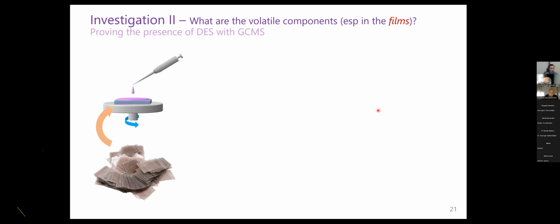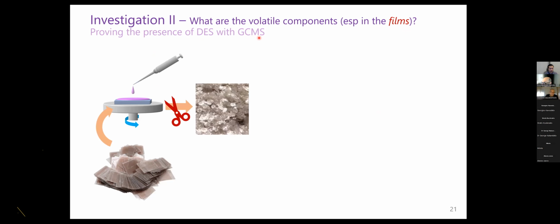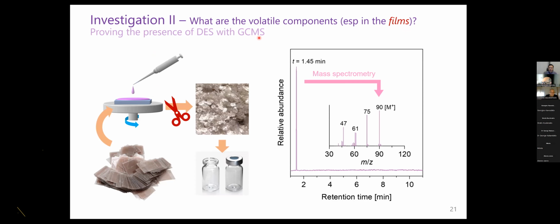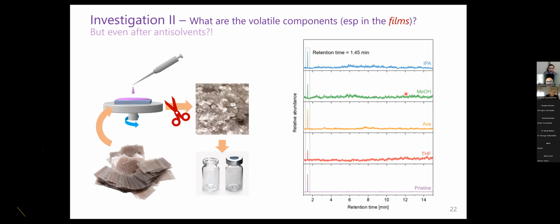Then we also studied the film state. In this case we tried to prove the presence of diethyl sulfide in the film state using gas chromatography mass spectrometry. We used a thin mica substrate and deposited the CuSCN directly on the mica, and because mica is very thin and brittle, we can just cut it into small pieces, put them in vials, and run the GC-MS. For sure, we find the signal of diethyl sulfide, and surprisingly, the same as when we tested the bulk material.